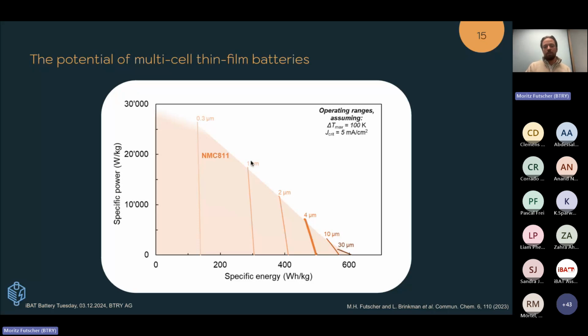And then you see here these lines, and these lines correspond to different cathode thicknesses. And you can see that if we go to very thin cathode thicknesses, we actually reach very high specific power densities in the order of 10,000 watts per kilogram. If you compare this to a classic lithium-ion battery, this is about a factor of 10 higher than what a lithium-ion battery can offer. But we can still offer this at a very high specific energy density as well. You see that we are still in the order of hundreds of watt-hours per kilogram. And this is especially true if we use very thin cathodes. If we use thick cathodes, of course, we are going into the regime of classical lithium-ion batteries, but also solid-state batteries.